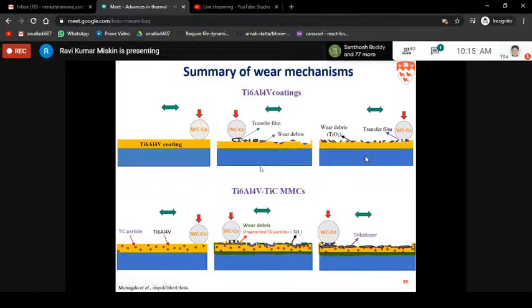Now when you come to the composites, that's the down image, there you have a titanium 64 matrix, and then you have small particles that are embedded inside that, and when you wear out, you start exposing these particles, and once they stabilize, then you have formation of tribolayers. That is the extreme image. So that's the tribolayer formation, and once you have tribolayer formation, you don't wear out your material. So that's the advantage of having a composite coating on your part rather than having a metallic coating.